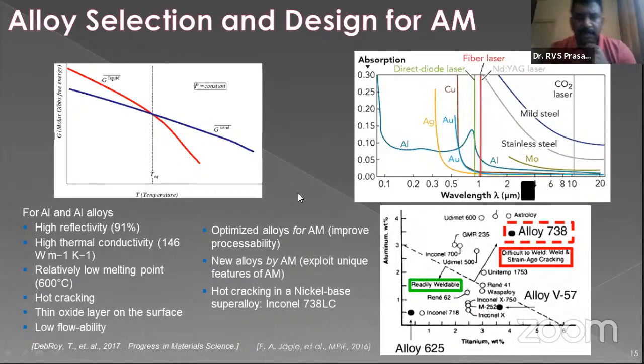So I will be touching upon the alloy selection and design for this particular additive manufacturing process. When you come to this materials selection, the important aspect is the free energy versus temperature diagram. You can see the free energy versus temperature diagram where the liquid and solid will be different. Once the free energy of that particular phase becomes lower, at higher temperatures the liquid will be stable. At the same time, solid will be stable at lower temperatures from this particular free energy temperature diagram. This is a very important aspect because when you're considering a new alloy or a new material, the melting point will vary with respect to different materials. For example, aluminum will have around 650 degrees in that range, and the other alloys like steels will be at very high, like 1500 degrees and above. So when we are considering melting point, all those aspects will come into your laser beam density calculations and laser power calculations and your scan velocity.